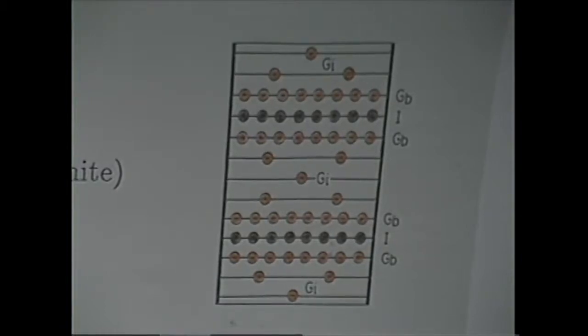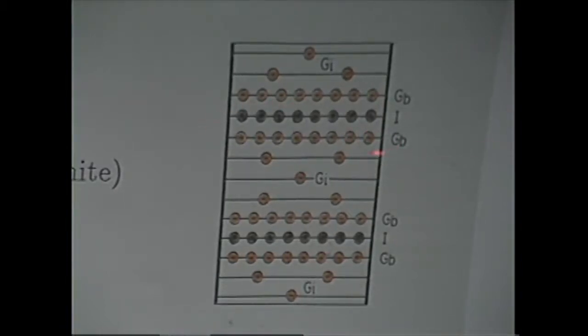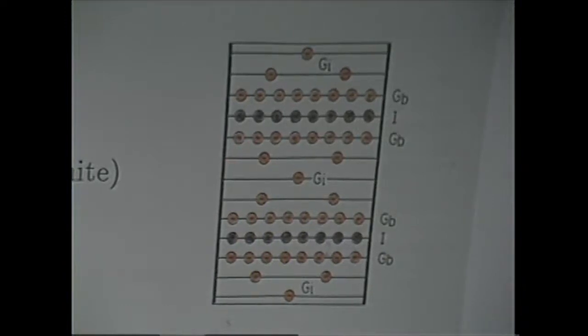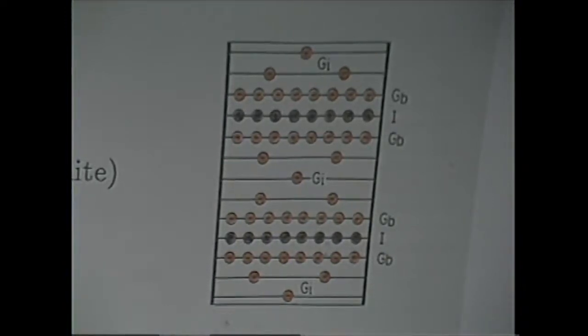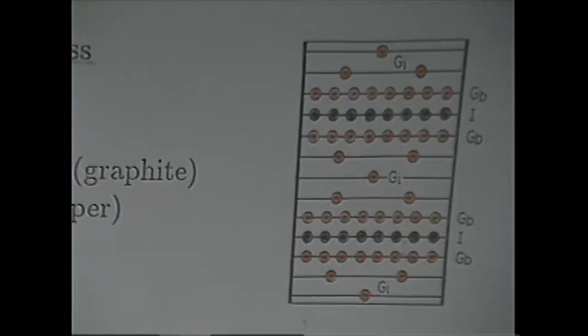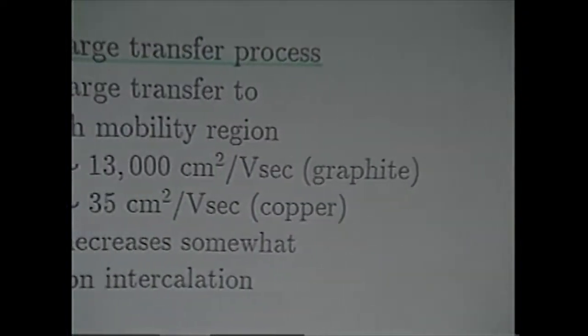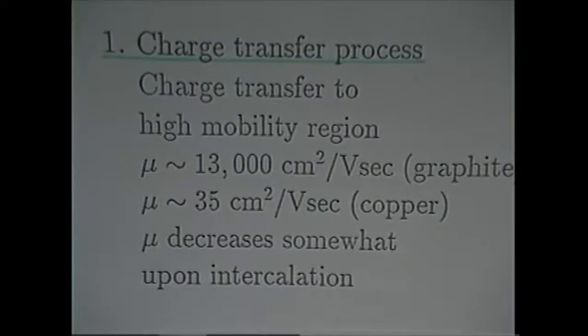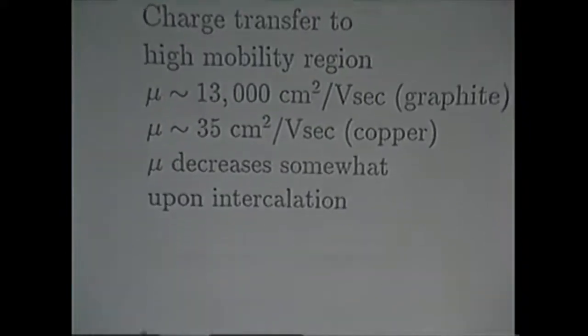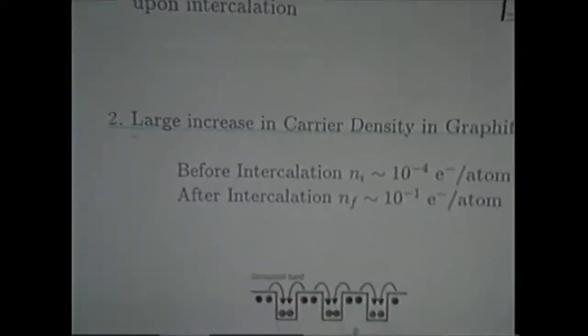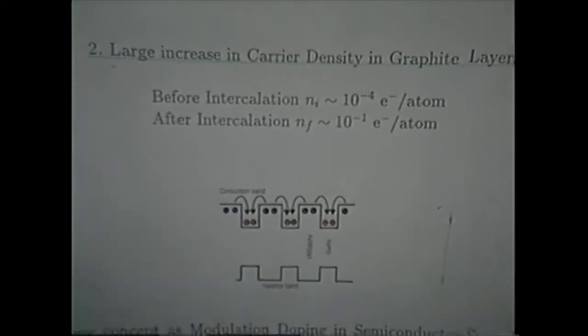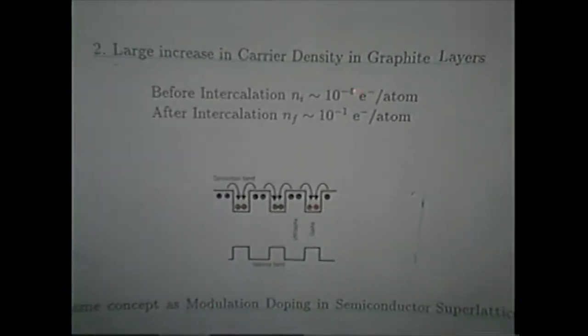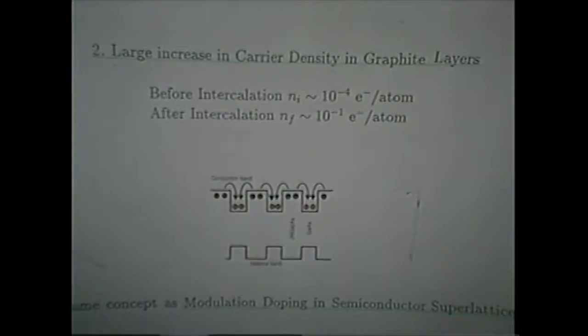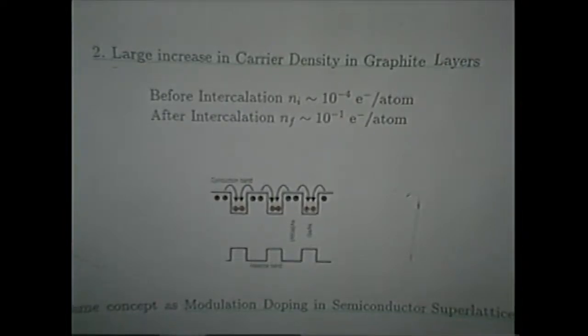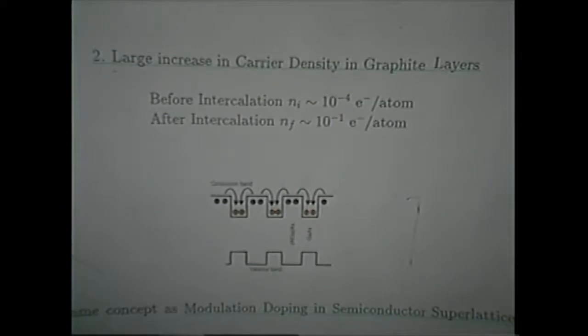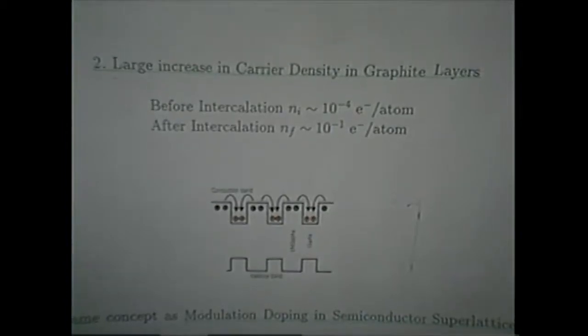So we'll develop a very large carrier concentration in the graphite bounding layers, very large compared to the carrier concentration in graphite itself, which has almost no carriers, 10 to the minus 4 electrons per atom at room temperature and less than that at low temperature. So intercalation allows the change in the carrier concentration by approximately 3 orders of magnitude. So in that way, it's possible to greatly change the transport properties of intercalation compounds.